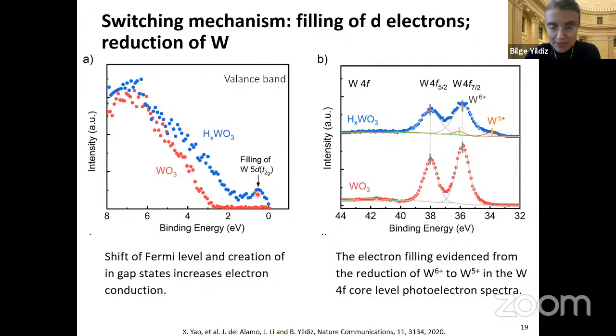So formation of this in-gap state that increases electron donation and carrier concentration is one reason for the increased conductivity upon protonation. And that's also consistent, that electron transfer to tungsten is consistent with our finding of tungsten 5+ that forms after protonation, whereas before it's only tungsten 6+. So that's on the carrier concentration increase.